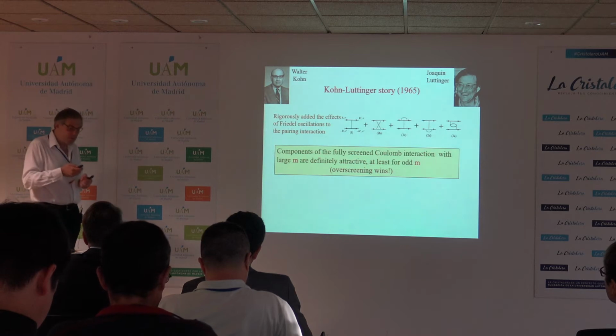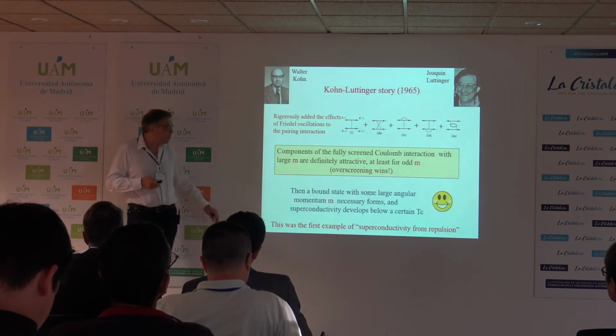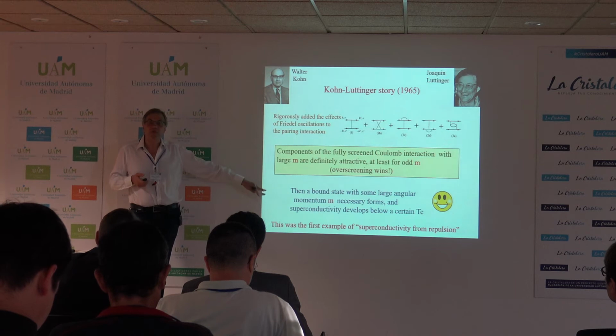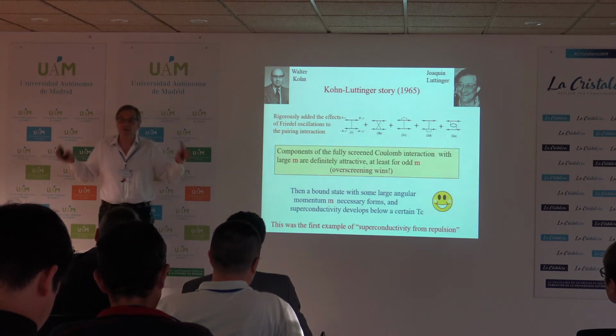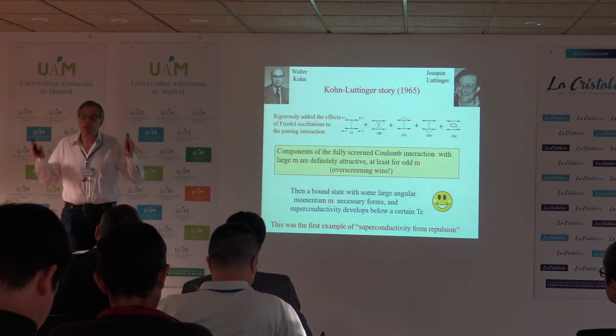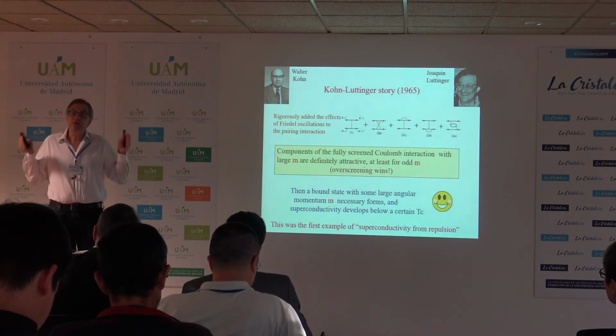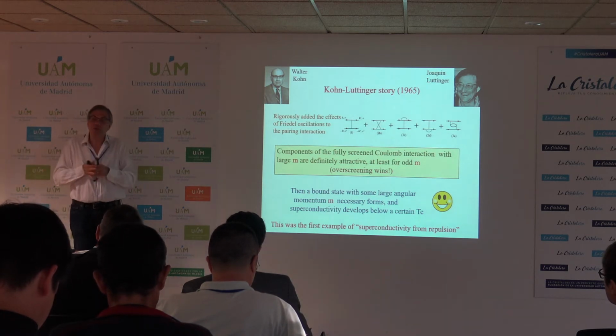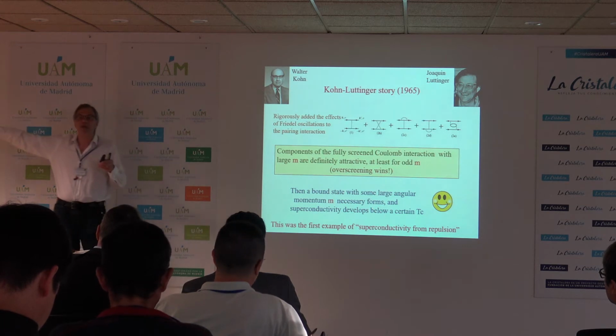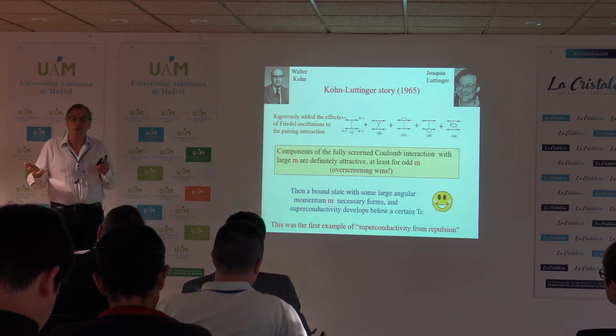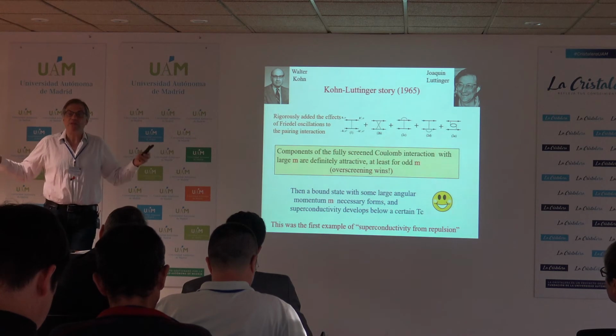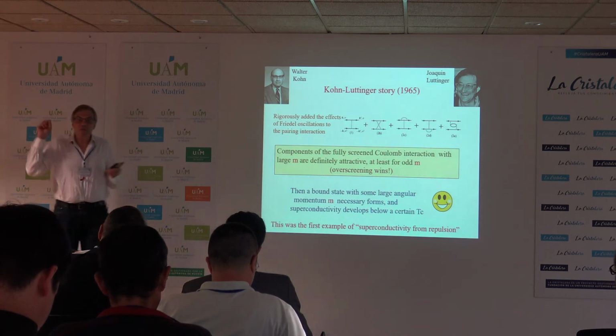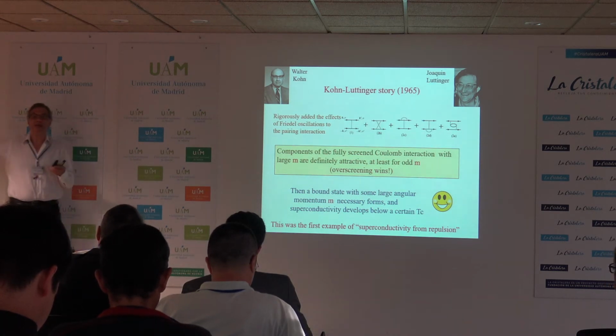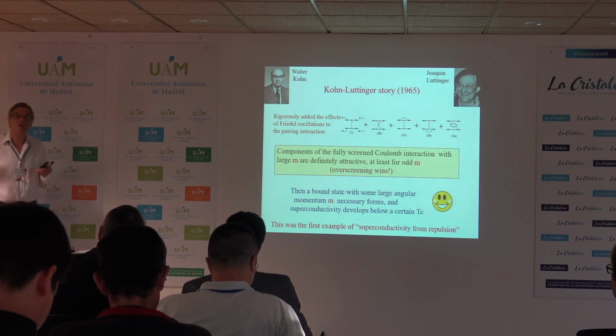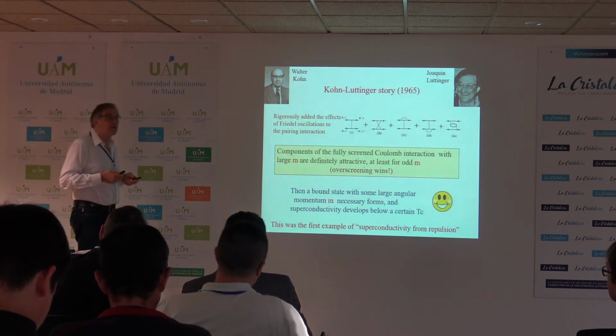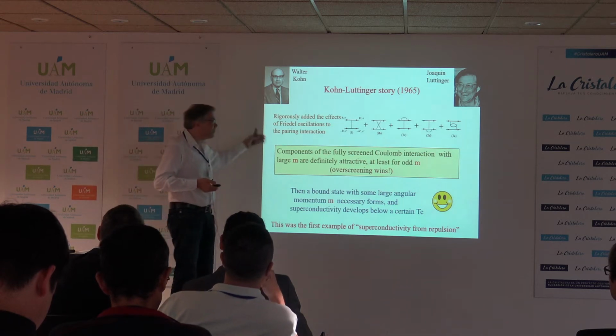And this was wonderful because this was the first real example of superconductivity from repulsion. You start with an electron-electron interaction, which is totally repulsive. You screen this electron-electron interaction, and because the screening introduces this oscillating component, there is occasional overscreening, which on average does very little, but if you zoom in on particular angular momenta, you find that this overscreening wins, and you get effective pairing, an attractive interaction.